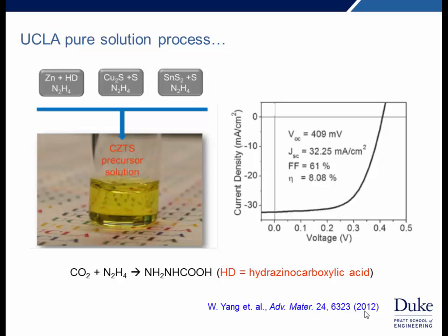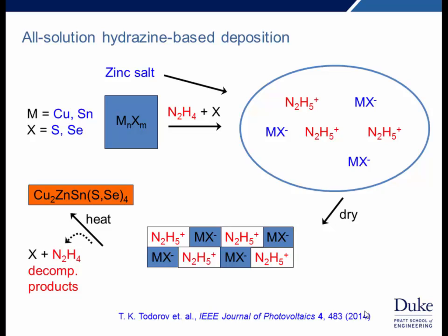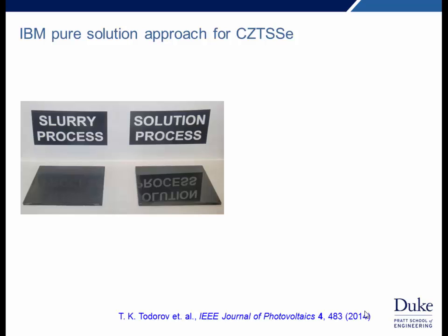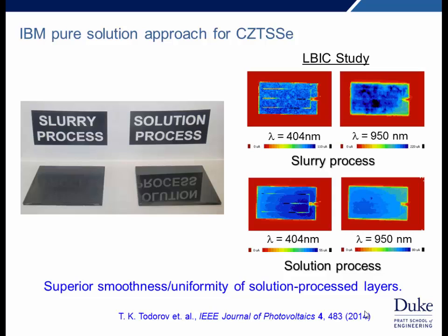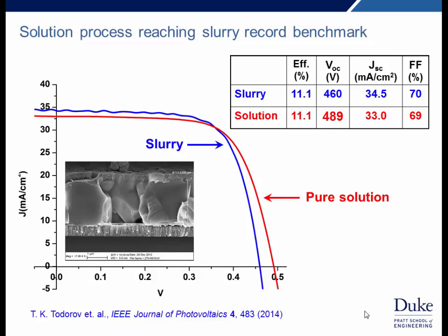And they were able to demonstrate 8% devices using this approach. We used a similar approach, but adopted a zinc salt rather than reacting the highly energetic reaction between carbon dioxide and hydrazine. And we're also able to create this pure solution, and then we followed the exact same approach we used previously. And using this process, you can see we get substantially smoother films. They're shinier, also more uniform. So these are light beam induced current studies, two different wavelengths for the slurry process and the solution process. And just visually, you can see that these solution process devices look more uniform. This did give some improvement in open circuit voltage, so maybe 5 to 7% enhancement in the open circuit voltage, and so that was encouraging.